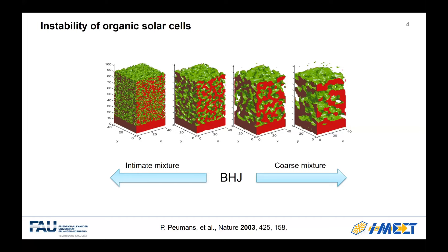For example, we used solid additives, compatibilizers, and cross-linkers. We also developed organic nanoparticles to try to fix nanostructure phases. After a long time, we figured out these concepts have advantages but also disadvantages, and we couldn't fully address the microstructure-induced instability. So we thought: maybe it is time to push this microstructure to the limit — either mix both donor and acceptor as much as possible to get a fully intermixed microstructure, or go in the other direction to get fully separated devices.